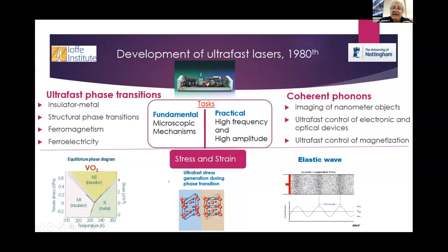Another point is that when phase transition takes place, whether equilibrium or photo-induced, the lattice changes. For us it's important that the lattice constant changes. First, the symmetry of the cell changes, which concerns mostly optical phonons, but for acoustical phonons it's important that the size of the cell changes, and then the lattice constant changes, resulting in strain.